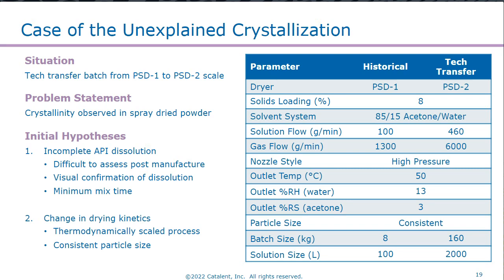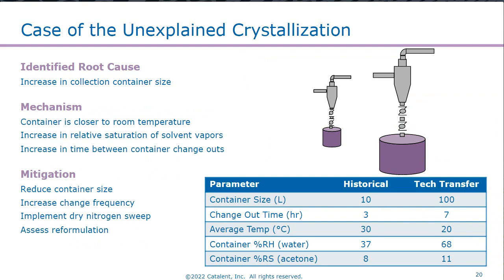solution. A few things we had in place to de-risk that were visual confirmation of dissolution, where the operators observe the processing tank and ensure that it's a clear solution, and a minimum mix time. The other hypothesis was that during this scale-up, we changed the drying kinetics of those droplets. This wasn't likely, though, because we had a thermodynamically scaled process and consistent particle size, meaning likely consistent droplet size between the batches. What I will draw your attention to is at the bottom of the table, we had a fairly large change in batch size and solution size, which had led to what we eventually identified as the root cause of the issue: a change in our collection container size.